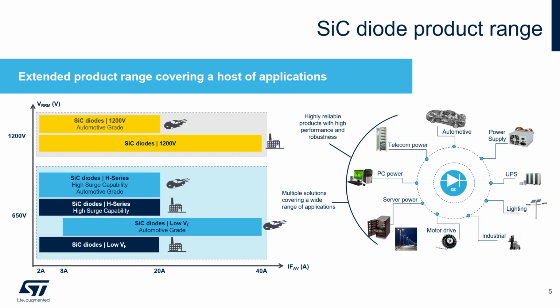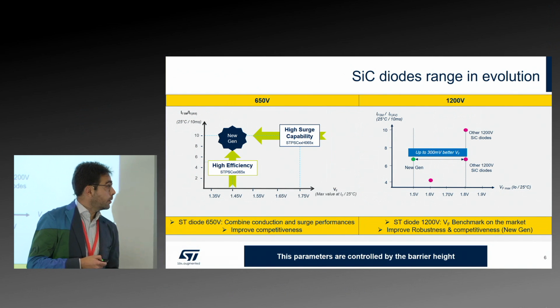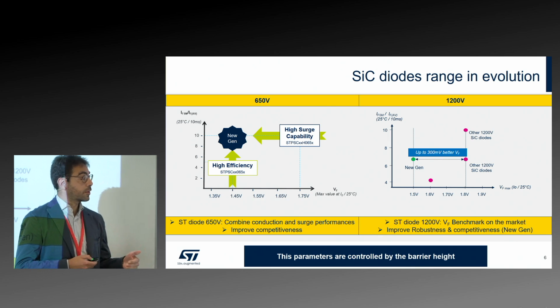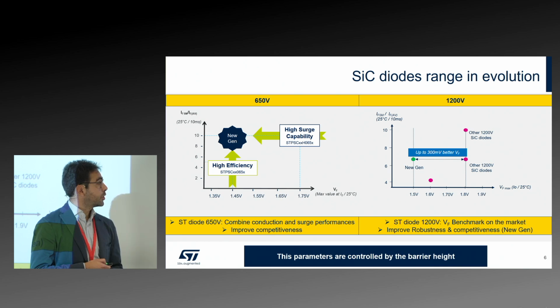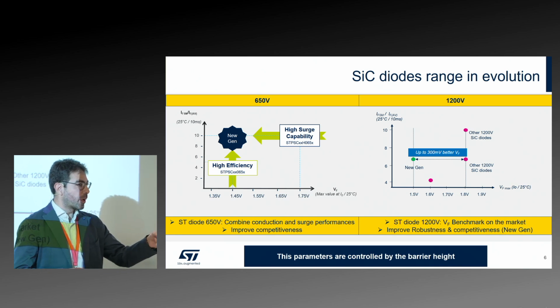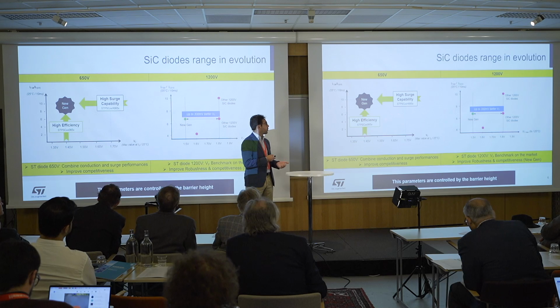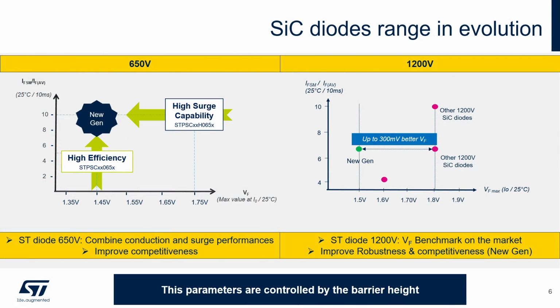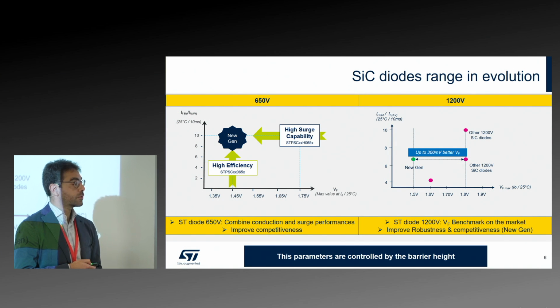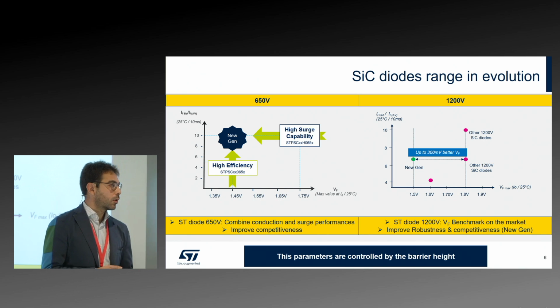Then we also have 1.2 kV, again qualified for automotive grade and industrial application, spanning from 2 to 40 amp. But again, for our silicon carbide diodes, research and development is really in the field. So for the new generation of the 650 V, which Victor said is the battlefield at the end of the day, we really tried to improve the performance. We lowered the forward voltage from 1.75 to 1.45, and we also doubled the surge capability. And for 1.2 kilovolts, we shifted our VF by 300 millivolts, increasing again the efficiency of our device.